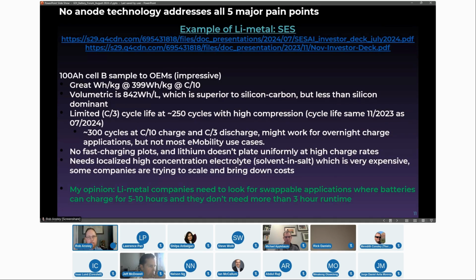There's only one real option to get to 1,000 cycles, and that's silicon carbon. And there's only one option to get massive, massive energy density once they've worked out all the other issues, if you don't give all the energy back with solid state and compression, and that's lithium metal. And then what you have to do is decide what your use case is. Depending on your use case, you're going to choose one of these three things as they all get to maturity and commercialization. Now, why don't we use real examples?